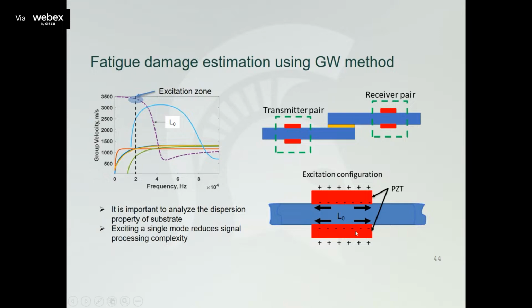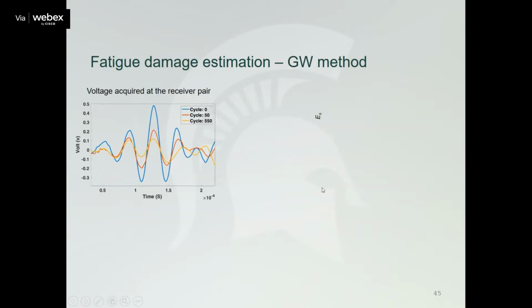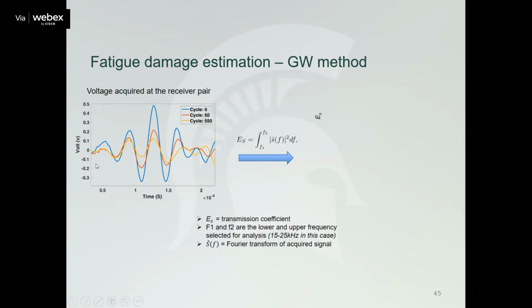You have the same setup, this is called lateral PZT excitation, to excite the L0 mode and let it transmit from one to the other. Well, you'll get this measured at different cycles. And you can see at different cycles of fatigue loading that the voltage acquired at the receiver pair, which is also associated with the energy being transmitted from one substrate to the other, is changing over cycles. And this definitely makes sense, right? When you have 0 cycles and compare to 550 cycles here, 0 is a resting stage, 550 you have some defects there. So definitely you're going to have a reduced voltage measured at the receiver PZT sensor.